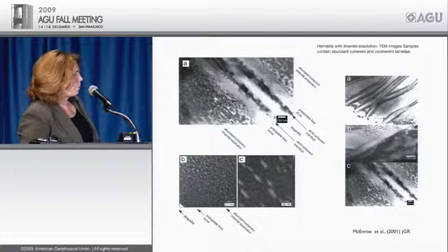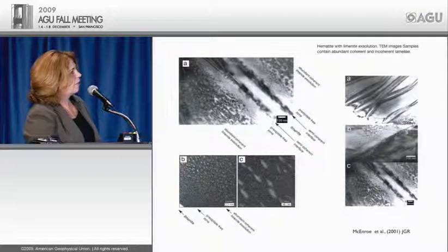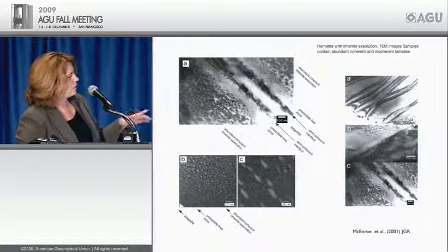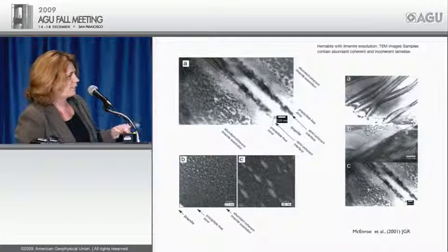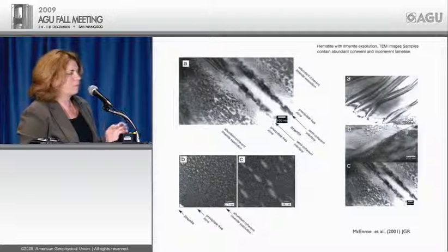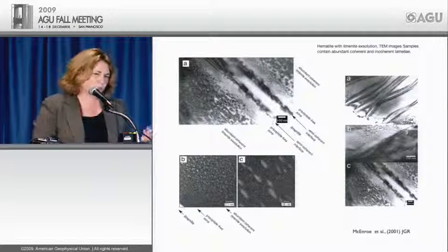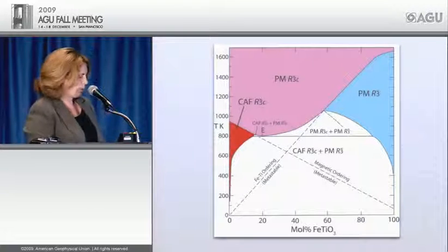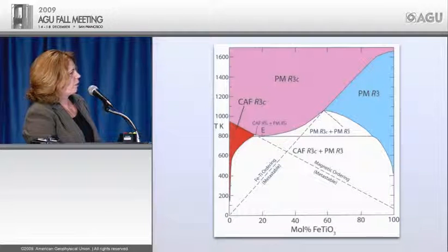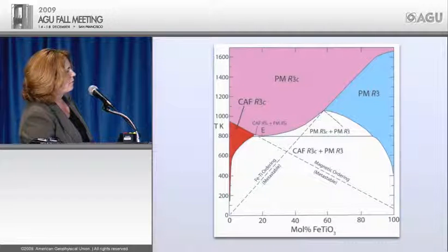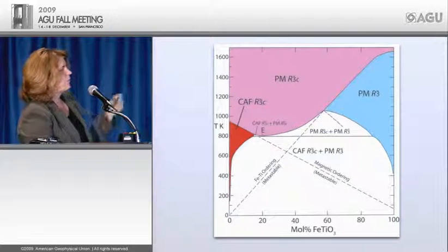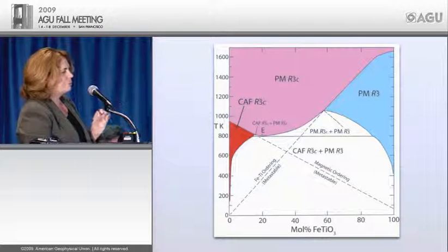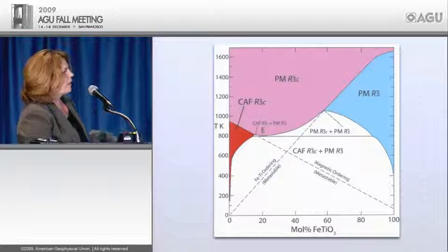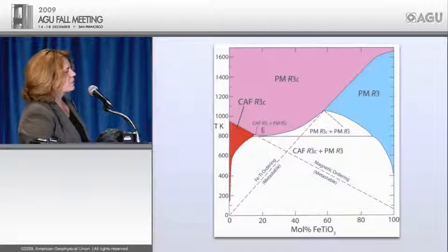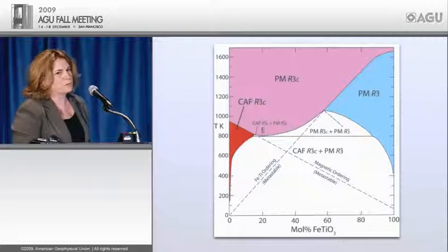Now, when we go on to the TEM, we find that these exsolution lamellae continue down to a very fine scale, and on the lower left-hand side there, you can see a scale bar of 10 nanometers and 20 nanometers. This exsolution lamellae continues to go down in size. Of course, we're getting to the point where actually these things should be superparamagnetic, which I'll bring up later. Now, we have to look at the phase diagram, and in the phase diagram, we see we have a canted antiferromagnetic field in the red, the paramagnetic disordered field in purple, and the paramagnetic ilmenite field, ordered, on the right. We have an order-disorder transition for the ilmenite ordering, and we have a magnetic ordering going from about 670 degrees centigrade, and it goes right down for the solid solution to 57 K for ilmenite.